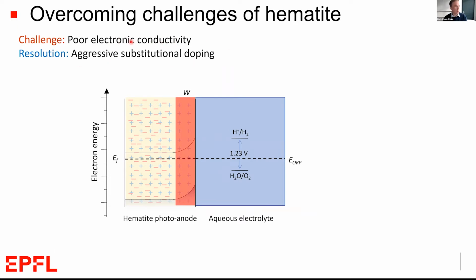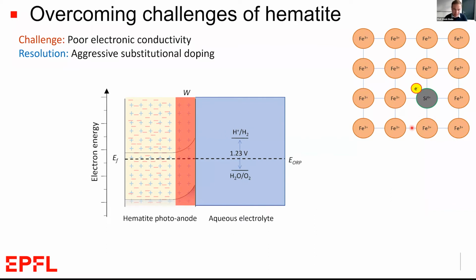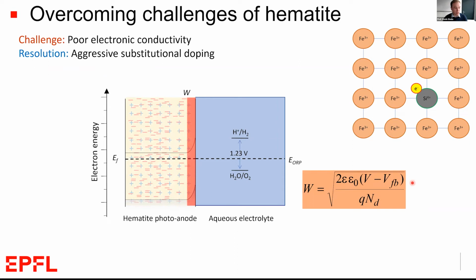We have to dope it to increase its conductivity. And as you probably know, we can dope a material by adding an extra electron, but that changes this electrostatic interface between the semiconductor here and the water, specifically the Schottky junction that's formed and the width of the Schottky junction, because the width of the Schottky junction is proportional to the inverse square root of the number of dopants that we add. That can be okay in the material if the diffusion length of carriers is high in the material.